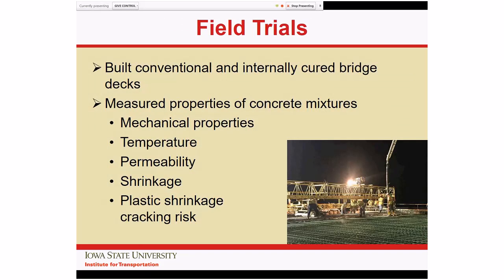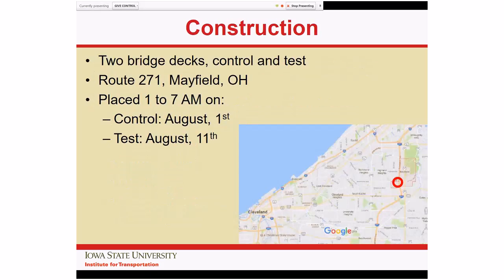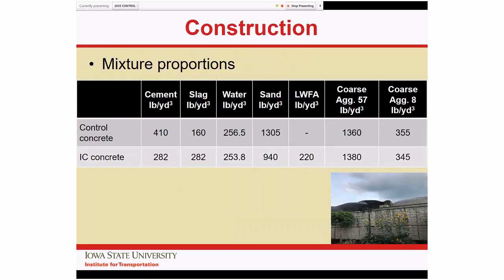And so we had a few discussions with the DOT staff and worked with them to set up a specification for a bridge deck, one with and one without the internal curing. And again, we measured the properties of the concrete mixtures. The two decks were on Route 271 in Mayfield, pretty close to where you all are right now. The control deck was placed on August the 1st, 2017. The test deck was placed 10 days later.